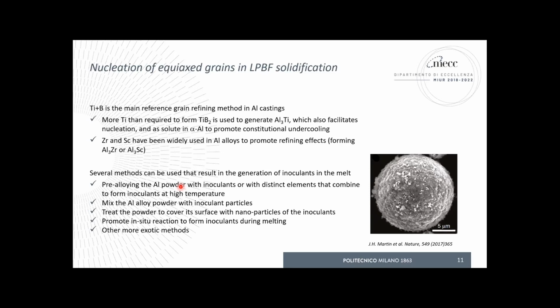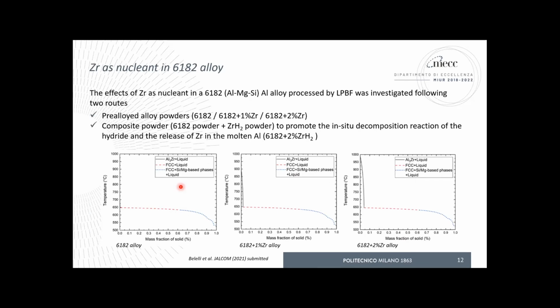We can pre-treat the powder particle surfaces to cover them with some nanoparticles of the inoculants. This is a very common strategy, and there are some papers in literature. It's very elegant. It's really wonderful in terms of scientific approach. It produces, in principle, a very good result because we are pretty much sure that the inoculants will be very homogeneously distributed in the melt and in the final alloy, but it's very difficult to industrialize this method. Or even we can promote in situ reaction between some ingredients to form the inoculants, to have a chemical reaction in order to form the inoculants through the melting, or there are some other methods. In the next slide, we'll try to show you some results about some of these strategies.